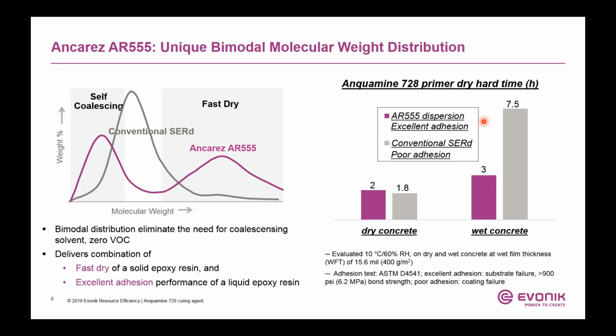So we compare Anquamine 728 performance with AR555 and standard solid resin dispersion on dry and wet concrete, and these are all done at 10C. Most of this webinar, we focused on 10C because that's the critical low temperature performance we focus on when we develop the product. So at 10C on dry concrete, the Anquamine 728 primer dries in 2 hours. On wet concrete, just slightly longer, it's 3 hours, and it has very good adhesion to concrete substrate.